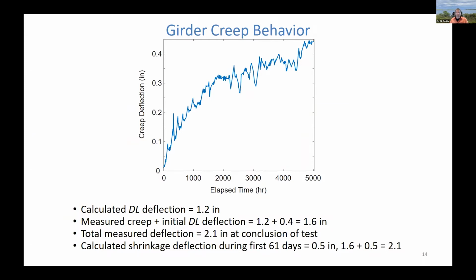And we see some initially higher creep deflections, and then it does tend to taper off a bit, in round numbers, about 0.4 of an inch, about the maximum creep deflection that we observed. We see some bouncing up and down because it was inside, but there are temperature changes and humidity changes within the lab. They do tend to affect deflections a little bit.